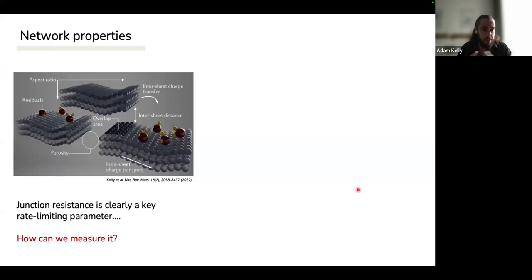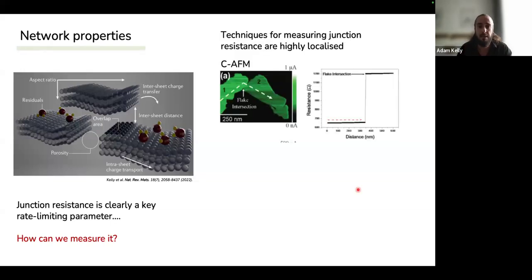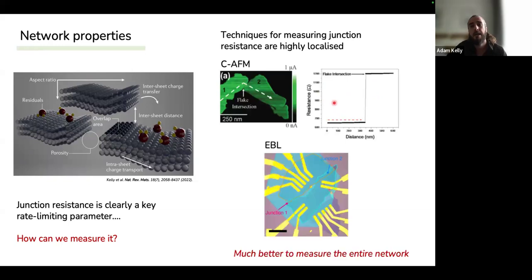So the junction resistance here is clearly a key parameter. The question is, we have this property, junction resistance, and can we measure it? Now, techniques for measuring the junction resistance tend to be very highly localized. We have conductive AFM, where we raster our tip along one nanosheet, and then bring it across the junction to the other one, finding a very well-defined jump in resistance that can be measured this way.